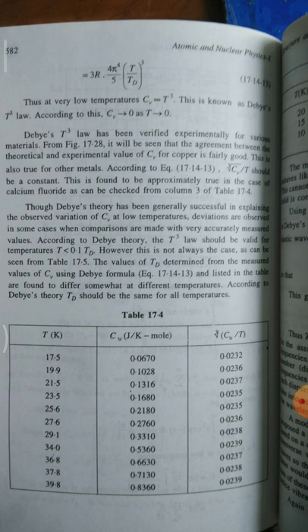According to Debye theory, the T cube law should be valid for temperature T less than 0.1 TD. However, this is not always the case, as can be seen in this table. The value of TD determined from the measured value of CV using the Debye formula and listed in the table is found to differ somewhat at different temperatures. According to Debye theory, TD should be the same for all temperatures. T in K, CV in joule per K per mole, and the cube root of CV by T.